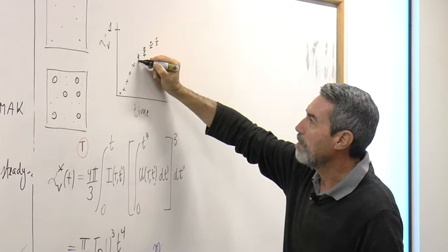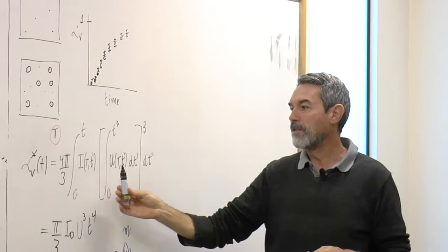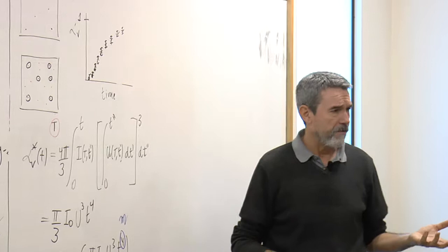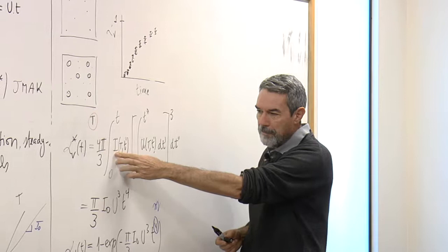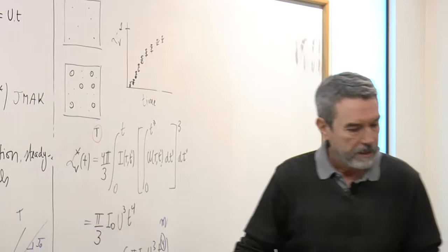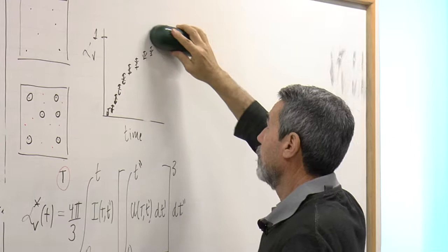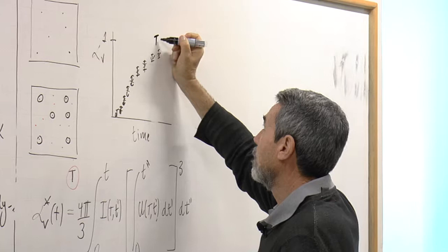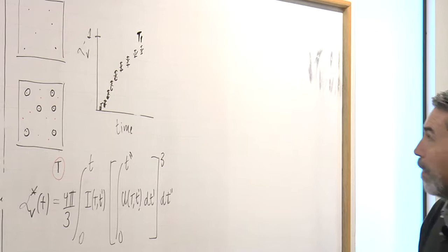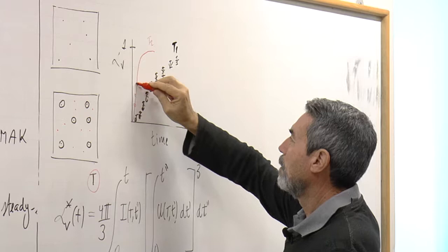But this is much easier to measure than either nucleation rates or growth rates. It's very time consuming, as we have seen before, and very delicate to actually measure the nucleation rates and the growth rates at different temperatures. Please recall that this is for a particular temperature T1. However, we can also measure the same kinetics, say at a higher temperature T2, another set of results, and so on.